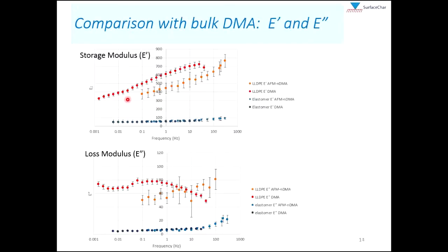If we now look individually at the storage and loss modulus data for these same materials. Up here we have the storage modulus, down here we have loss modulus. Focusing on the storage modulus, again, red is bulk DMA for linear low density polyethylene. The dark blue is the bulk DMA for the elastomer. This is the AFM-nDMA for polyethylene, and light blue is the AFM-nDMA for the elastomer. We can see on storage modulus, there is excellent agreement for the elastomer between the bulk and the AFM-nDMA. For the stiffer material, where the tip is going to be penetrating a little bit less into the sample, our AFM-nDMA values are a little bit low, but still within 25% or so of our bulk values.